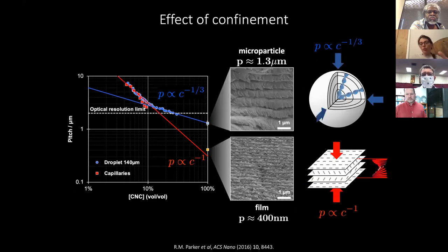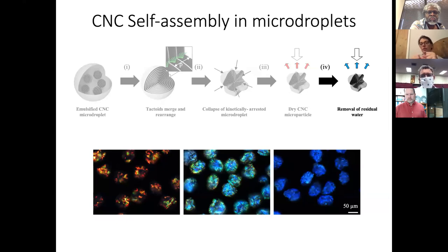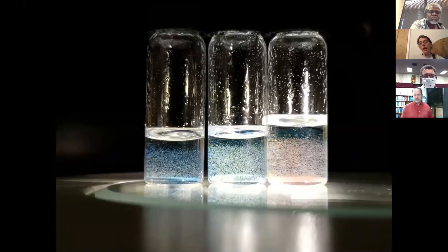And by controlling how much you buckle, essentially you can change the color. So removing the water completely will allow you to obtain particles that are essentially blue. Then if you swell them a little bit, they go into green. And then if you reintroduce water into the system, they can go again to the red, because you are essentially increasing the pitch, but these are the same particles. And we actually exploit this trick in what we call photonic pigments. In fact, these are particles of cellulose that are dispersed in water. And as you can see, we can make them from blue to gray, to green, to red.